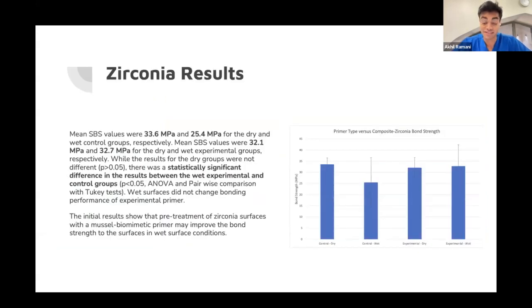And then the results: we saw that the mean values were actually significantly different for the wet experimental and control groups. We did not see a difference in the dry groups. So we were able to see that the wet surfaces actually did not change the bonding performance of the experimental primer. And so the initial results showed that the pretreatment of zirconia surfaces with the primer may improve the bond strength to the surfaces in wet surface conditions.